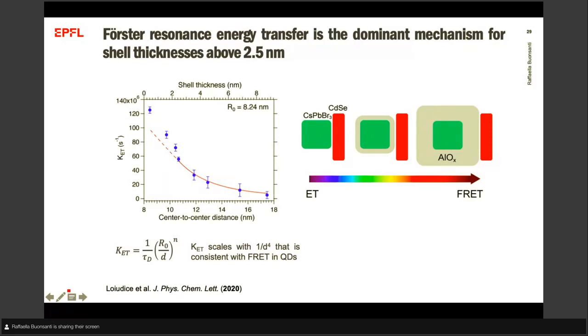What we found is that having this oxide shell builds a platform to control the way in which electronic energy is transmitted from one quantum dot to the other, in the sense that when we are below 2.5 nanometers, electron transfer dominates. As we start to go above 2.5 nanometer shell thickness, then we can have energy transfer as the dominating mechanism.